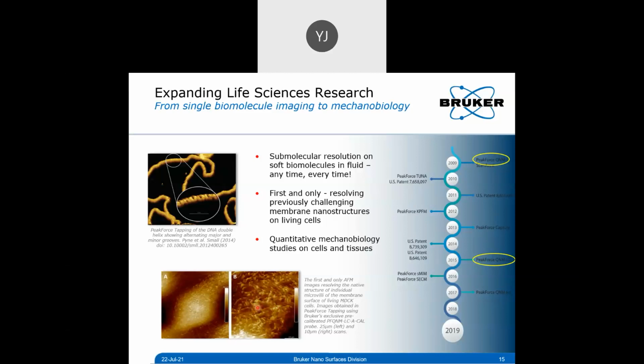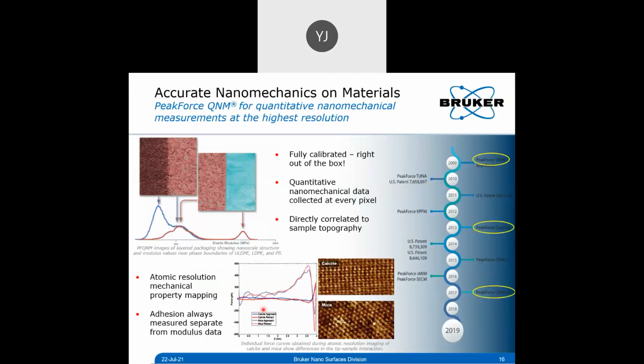And even the force that is used in tapping mode is too high for this kind of imaging, right? Usually you will destroy them, even if you use tapping mode. So doing that with PeakForce Tapping is the only possibility here. You can now control the force levels in piconewtons, right? 50 piconewtons pretty easy, maybe even single-digit piconewtons. And you can do the measurements on any kind of sample there.